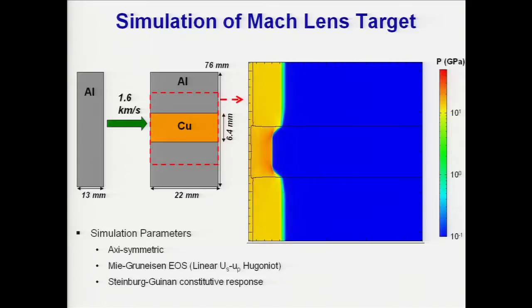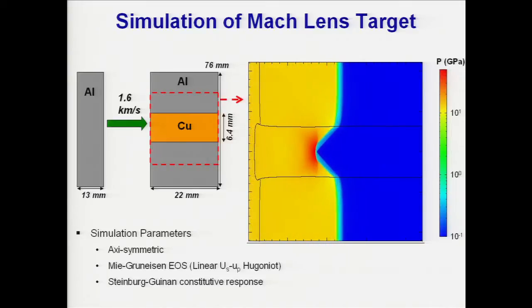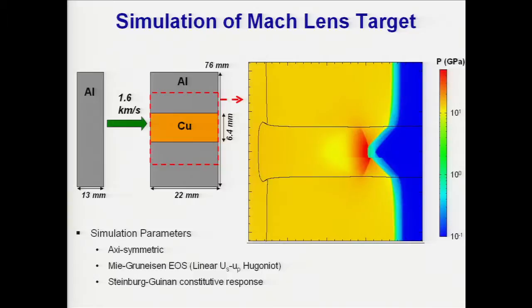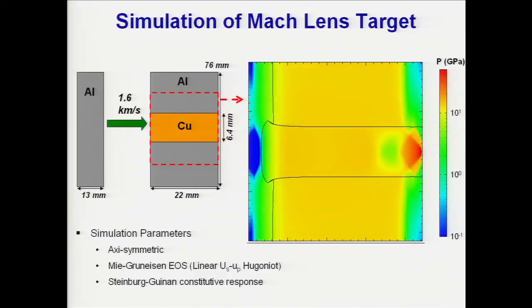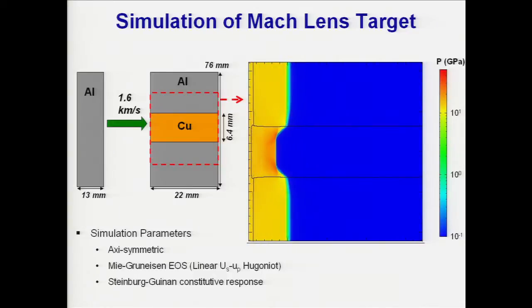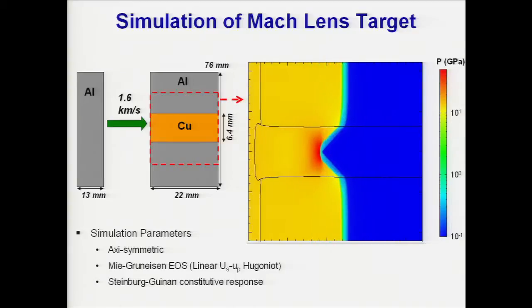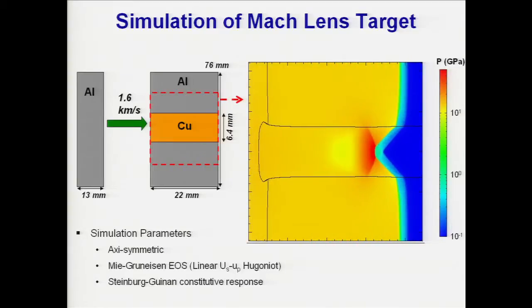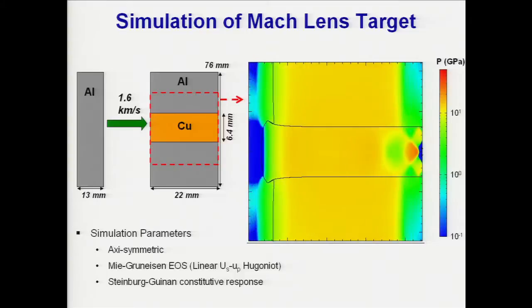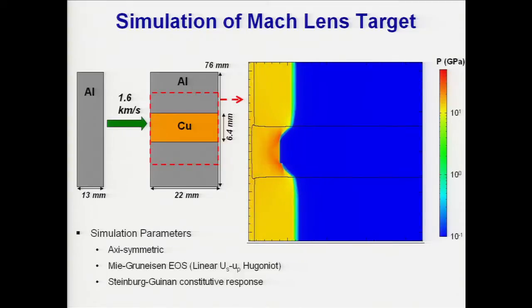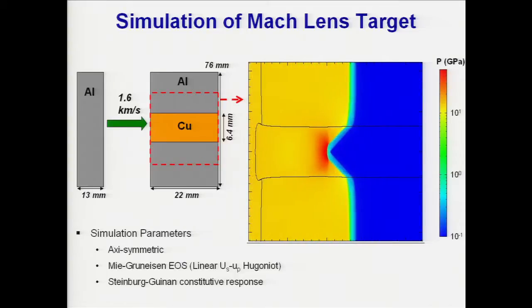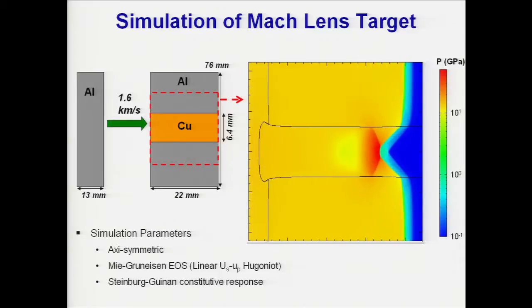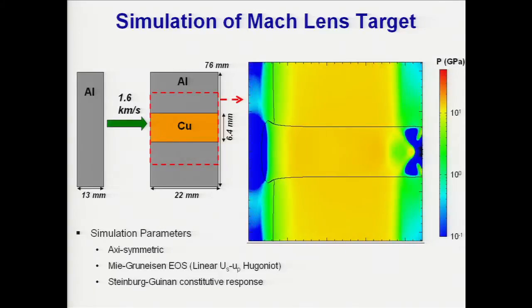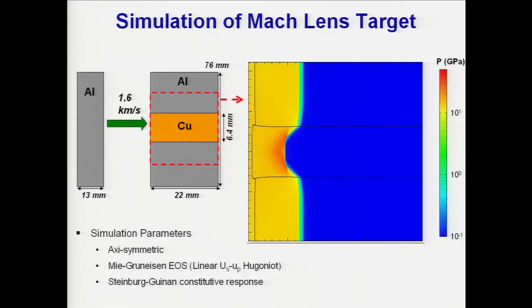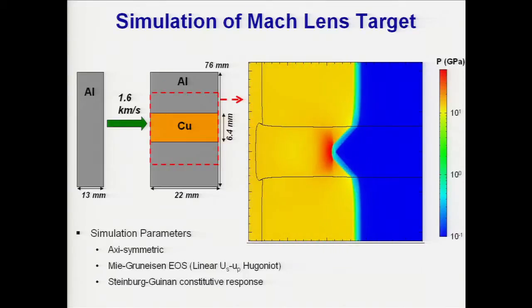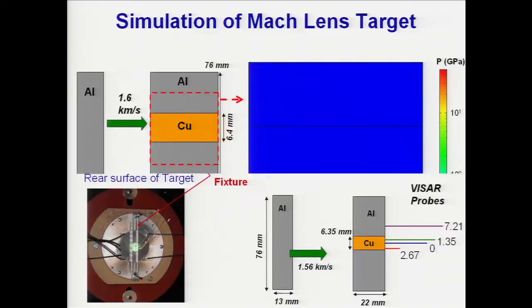And I'll show you the movie to show that, in fact, this occurs. Initially, we introduced the plane shock in the material, and then this collides. Now you create the Mach stem, which propagates at the same speed as the outer material. This way, we can create very high pressures at the center. You can see the pressures which we should get are in this range, but in the center region, we are getting high pressures. So we can amplify the pressure by using this technique, by these concentric cylinders.